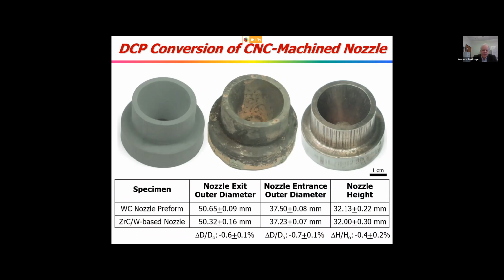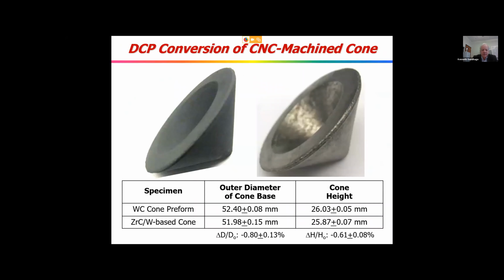So we measure the dimensions, the large diameter on the bottom, the smaller diameter on the top, and the height, and it hardly changes. The tungsten carbide preform, the large diameter was 50.65 millimeters, and went to 50.32 millimeters. Typically, we get about a 0.5% shrinkage. That's 300 microns difference between those diameters, not much at all. We've done other shapes as well. In this case, we green machined a cone and converted it, again, very small dimension changes.